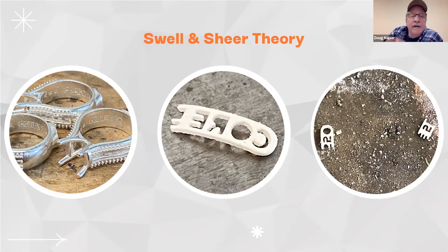So just keep an eye on these things and evaluate them before they actually get in there. And especially lettering has got a bunch of sharp edges and thin areas. The centers of O's and A's and R's and all that stuff is just very fragile. And with wax, it's no problem because that wax just melts out. So there's really nothing that's affecting the investment. But with the resin, it's transforming a little bit in there, and any thin areas and fragile areas, it's going to bust those out.